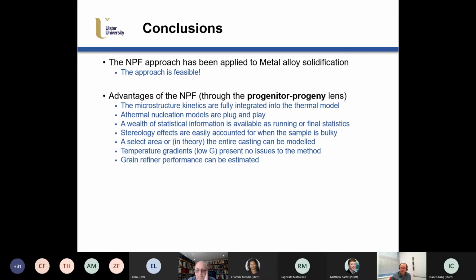Grain refiner performance can be estimated, so we can look at grain refiner efficiency. It has already been extended to the CET. So the nucleation progenitor function approach that I've presented today was also the basis of the equiaxed modeling in the CET modeling that I showed you at the very start. And so it does go into the high temperature gradient regime where you would have columnar growth as opposed to equiaxed growth. And more importantly, we've been able to model not just different phases, but different morphologies of phases, which I think is a nice addition to any modeling previously done.